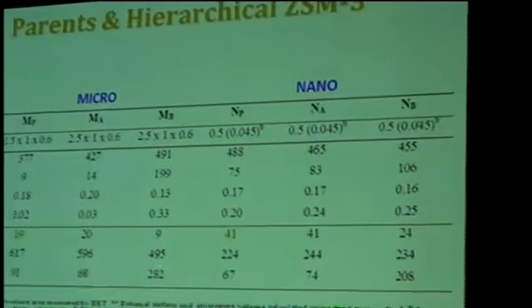You barely touch the number of active sites by doing the fluoride treatment, and you reduce significantly the number of active sites in the base treated material. In addition, it's a complication that I will not go into here, but you create a substantial level of extra framework aluminium which acts as Lewis acid in this reaction. Okay, so now we are going to look at the test.